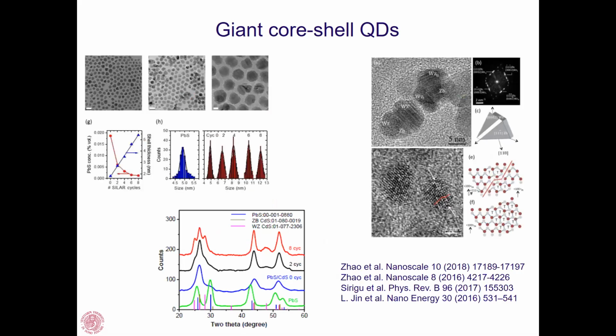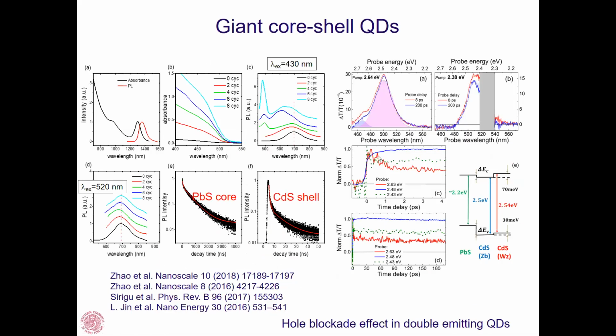We tried to fabricate giant core shell structures active in the infrared region, so lead sulfide, cadmium sulfide quantum dots. Here the issue is to understand the structure of these materials, and it was pretty challenging to identify the presence of lead sulfide. But then, coming to the optical properties, you can see that these crystals present a double emission.